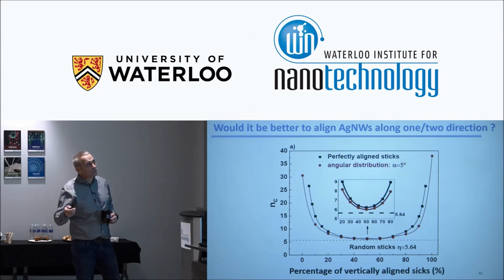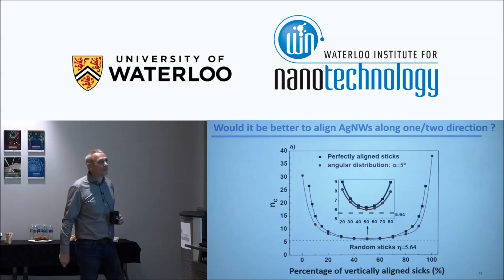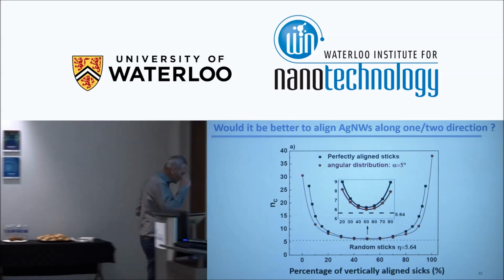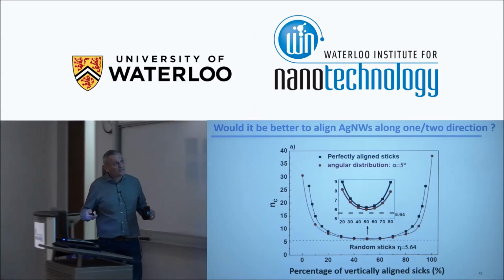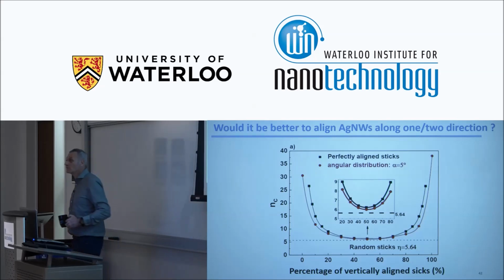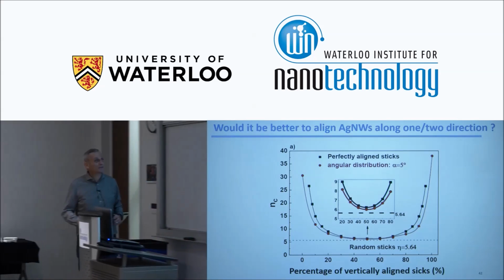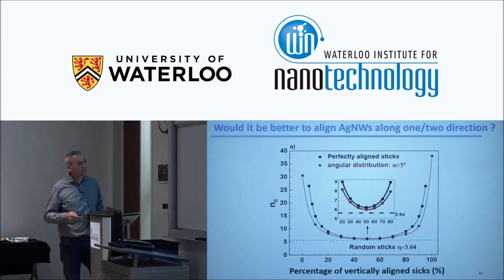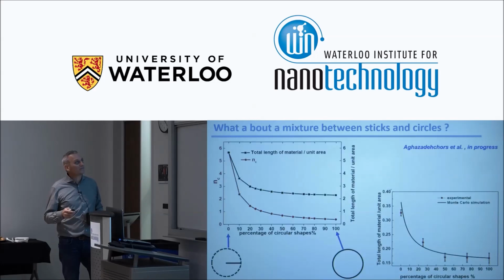suppose the diameter is 0, so only sticks. But if we allow an angular distribution of 5 degrees, it's slightly better, but we are still above the critical density for a random network. For us, that means that the random network is cool, maybe better than having some alignment along the X and Y axes.